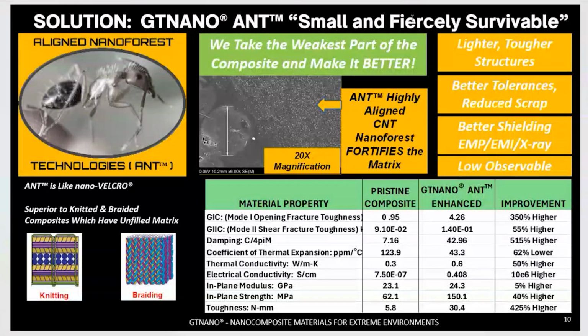It can also be used to make low observable composites like on the F-35 and the F-22. So for the Navy, we made 3 composite systems. We made a carbon epoxy that was reinforced with the nanoforest, with the ANT technology, and we made that a hell of a lot better. We also then took bismaleimide, which is the skin of the aircraft, and we improved upon the material properties of that composite system. And finally, on the inside of the engines, you have stator blades, which are made of metal, and some high temperature polyimides, and we made those a lot better.